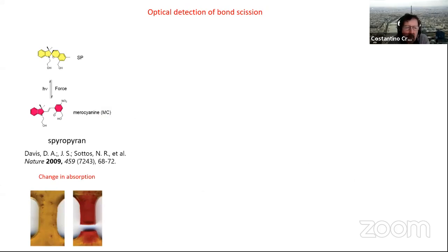Now, the topic is really about using mechanochemistry, as Tian was saying. So in the last 10 years, or maybe a little bit longer now, synthetic chemists have developed some molecules, or maybe they have pointed out that these molecules could be used to detect some changes in materials. And the idea behind this molecule is really about optical detection. The first one, and maybe the best known one, is spiropyran, this one here on the top left, which has a closed cycle. If you actually apply a force to that molecule, and I'll show you that this can be done at the molecular level, one of these cycles opens up, and this is a reversible reaction, and turns into a different molecule that actually has some fluorescence and also absorbs in the visible wavelength.